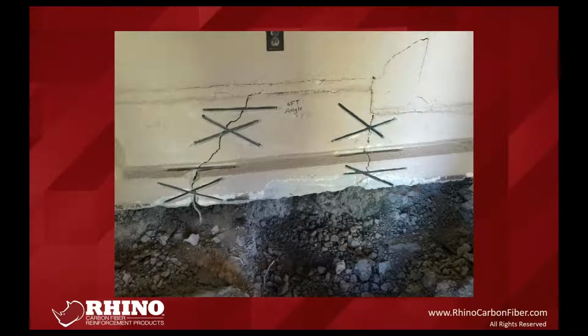In this application, the crisscross method is preferred, just because not only are you trying to stitch it together, but you're obviously going to be driving off of the bottom of that pier, so you could end up with some differences of pressure on that footing itself, especially since in this case it completely cracked and dropped. So they went ahead and did the crisscross method just to make sure that they had the tensile strength in multiple axes.